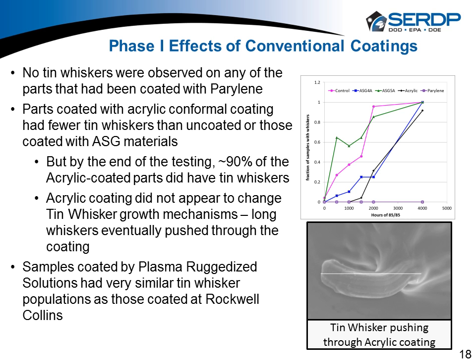There's still an acrylic coating over the top of it, but it's worked its way out. So by the first couple thousand hours, of course, the conventional coatings looked better than anything. By 4,000 hours, everybody got up towards what our controls were showing. A little tough time looking at Parylene. Parylene's a very uniform coating put down by vacuum deposition, but even with the Parylene, we got to that point.